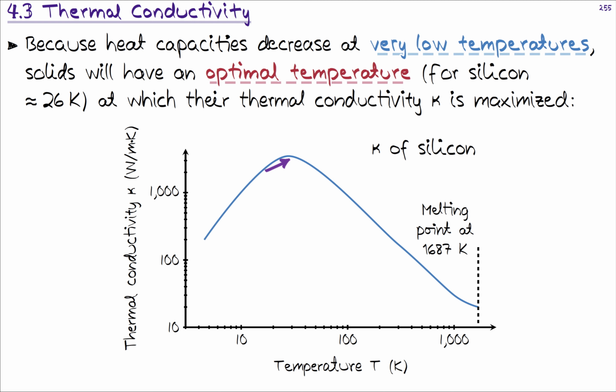And for diamond, because it's mechanically quite stiff, this sweet spot, if I remember it correctly, is moved towards room temperature, and that's the reason why diamond is really such a good thermal conductor. Because looking at this value, we see that this is actually quite high, around 3000 watts per meter per Kelvin. But the fact is that when we are dealing with room temperature, somewhere here, we have already gone quite a bit down from the optimal value in terms of silicon. But depending on the materials, the slopes are different, but the overall trend will be similar.